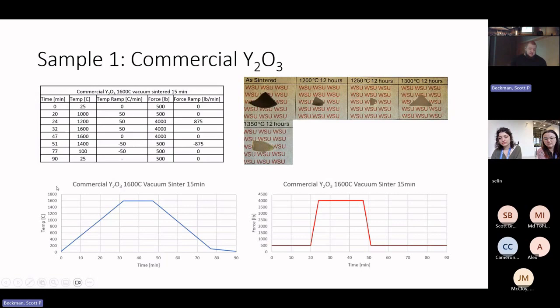We would heat them linearly from about room temperature all the way up to our sintering condition, in this case 1600 degrees C. We'd then allow them to dwell for 15 minutes, and then we'd again pretty linearly ramp them down to lower temperature before releasing the force during this ramp down, and then we'd have our finished product.